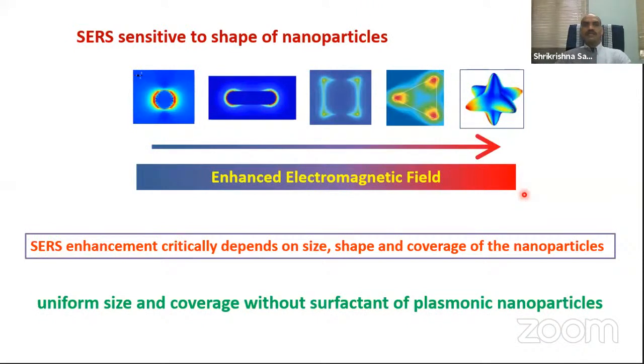Another thing you can see is that the enhancement depends not only upon the size of the nanoparticles or the separation between the nanoparticles, but also upon the shape of the nanoparticles. For example, if you are having a spherical nanoparticle, you can see that the electric field is restricted only to the surface, and whenever you go away from that, the red color means higher electric field and the blue color means lower. So when I'm going from yellow, red to blue, you can see that the electric field is decreasing. Similarly, if I'm having nanorods, it will be only at the edges of the nanoparticle. When you are having cubic, then at the edges, you can have triangular shape, you can have, for example, star shape.